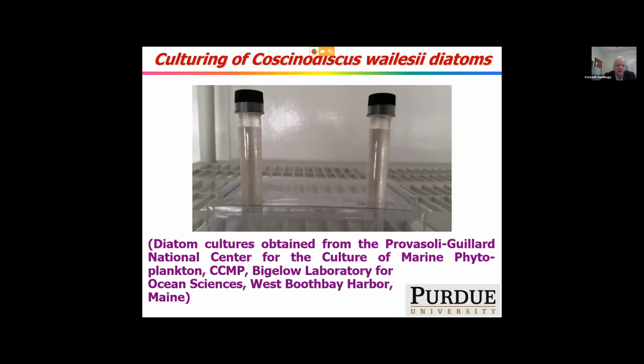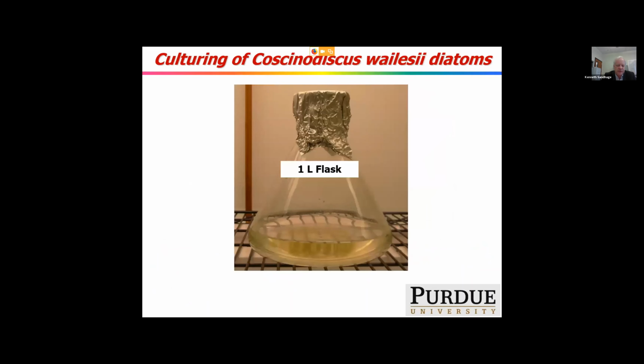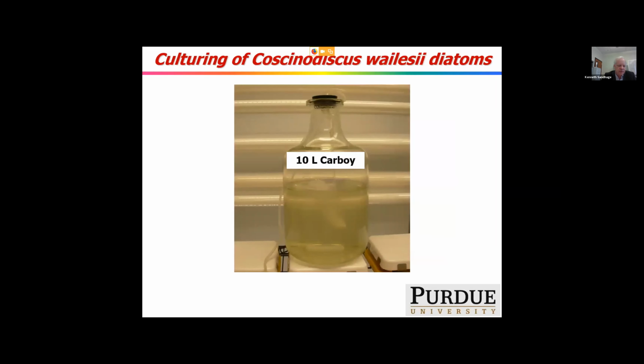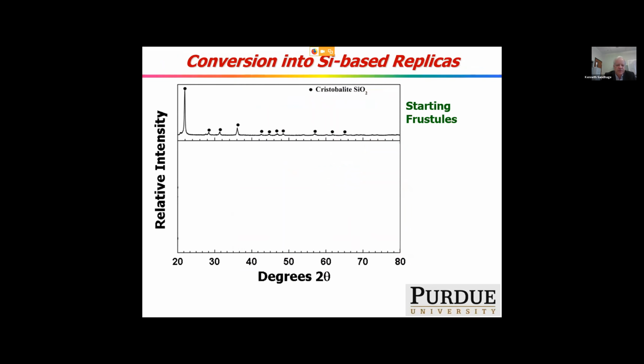We have a diatom culturing chamber in my group, and we culture them in ever larger containers. You can see it's a yellow-green type algae. We've gone up to actually 200 liters in some cases. And this is in a chamber with controlled temperature, controlled lighting conditions to mimic nature. So we harvest them in a centrifuge, and then we burn away the organic, and we can see by X-ray diffraction we have silica here.